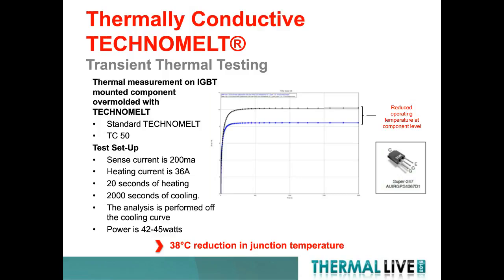What you see in the difference in these two curves is, one, the standard curve on the top, and two, the curve with the part molded with TC50, or the thermally conductive encapsulant, on the bottom. Again, this is a molded IGBT, so something that would have mold compound already around the device itself, mounted onto a PCB, a green circuit board, and then molded over the top using the Technomelt materials.